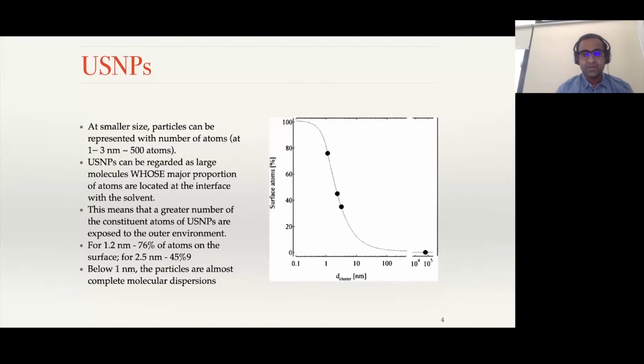So this just gives you an idea that by increasing the size, in this case almost doubling it from 1.2 nanometer to 2.5 nanometer, you're seeing a significant reduction in the percentage of atoms present on the surface. And if you reduce the size of the particle below 1 nanometer, then the particles are almost completely made up of molecular dispersion. Now, I said to you earlier, what is the big deal? Why do you want to reduce this size?